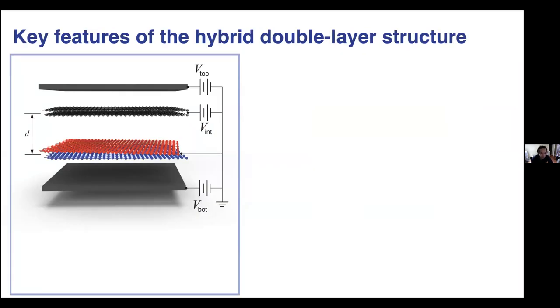There are two key features of this hybrid double layer structure that make this experiment possible. First, we have independent electrical contact on each active layer, which means there's a graphite top and bottom gate electrode, and also the Bernal and twisted bilayer graphene. You can see that we can independently control three voltage biases that give us independent control of three different experimental parameters: the density in the Bernal bilayer graphene, the density in the twisted bilayer graphene, and also the perpendicular displacement